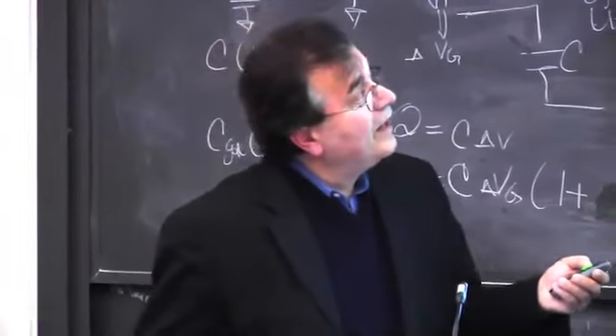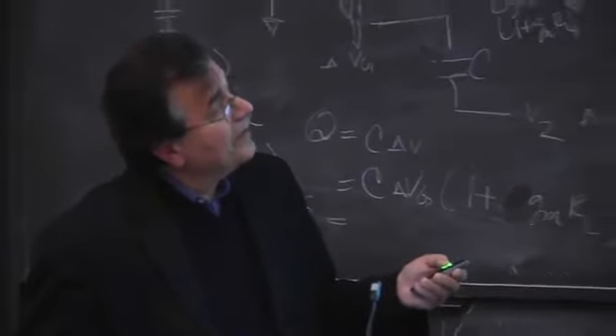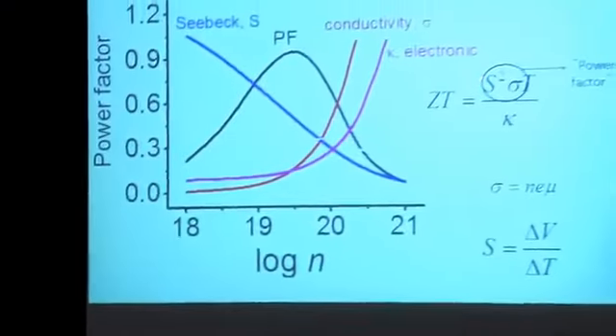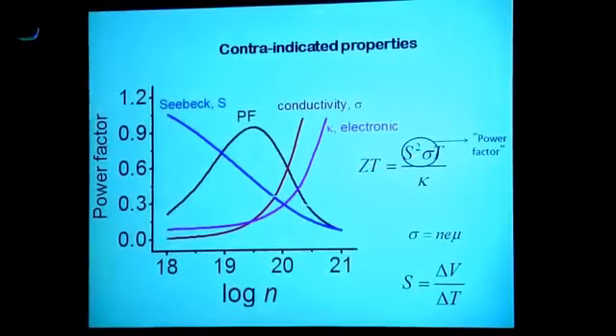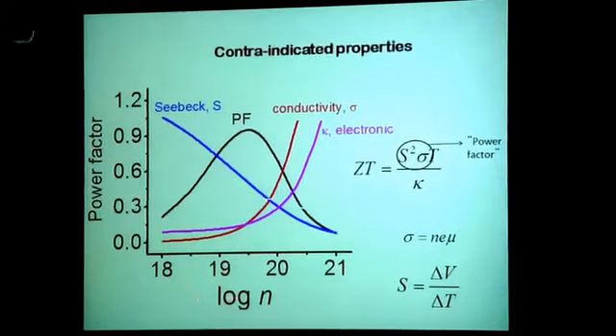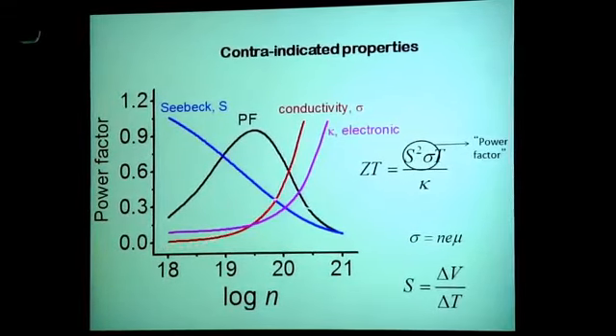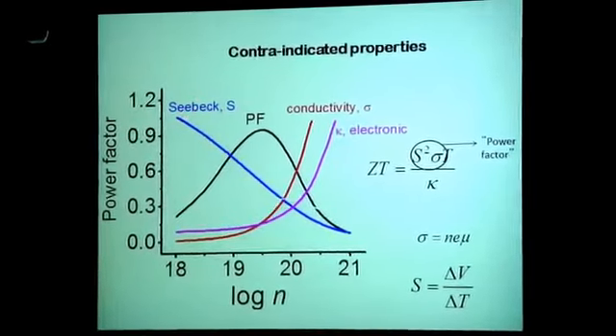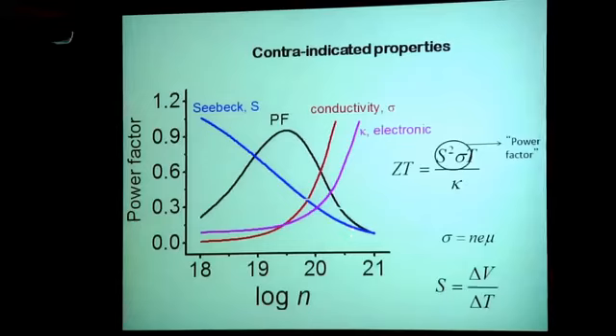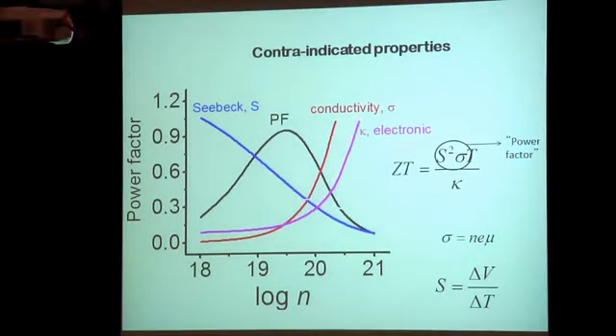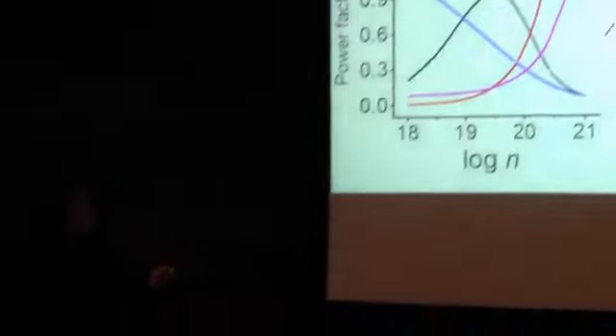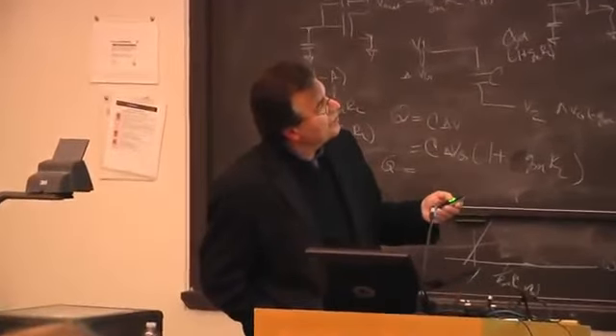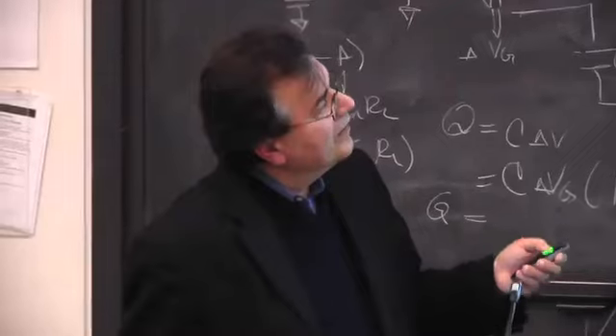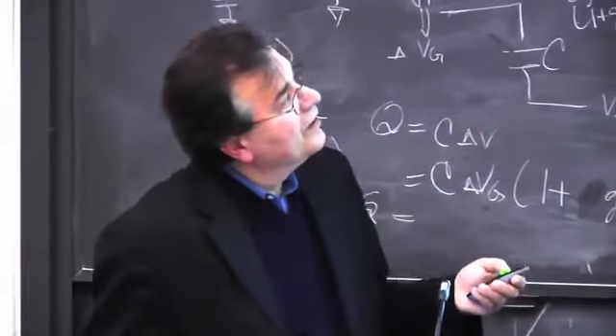But here's the problem. These properties are not independent. You raise one, you lower the other. They're contraindicated. So the power factor. So let's look at first as a function of carriers. So in a material where you can change the carriers, the more carriers you put, the more conductivity you have. However, the Seebeck goes down. It's predicted to go down. Also, the more carriers, you get more electronic thermal conductivity. So somewhere in between, there's a sweet spot for the power factor, which is the product. And you need to find that sweet spot, and hopefully that would be high enough to make it worthwhile.